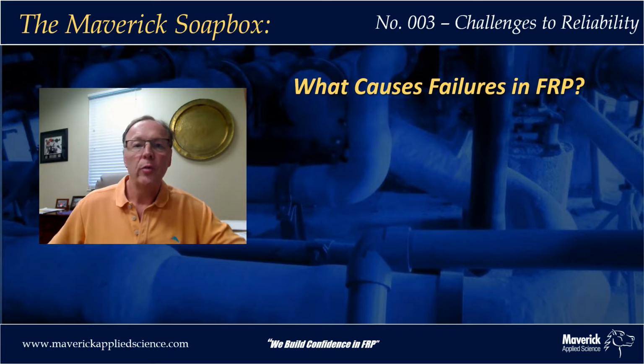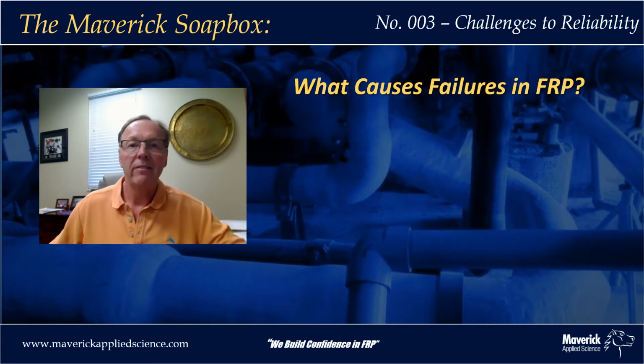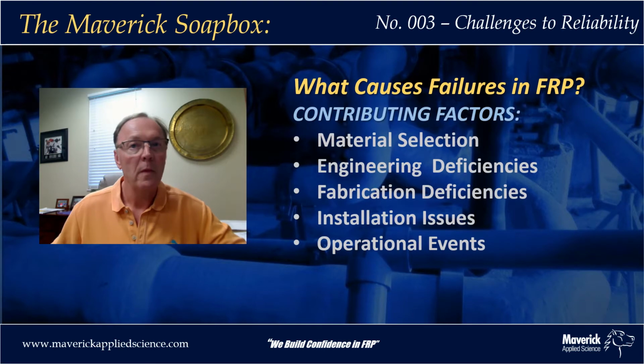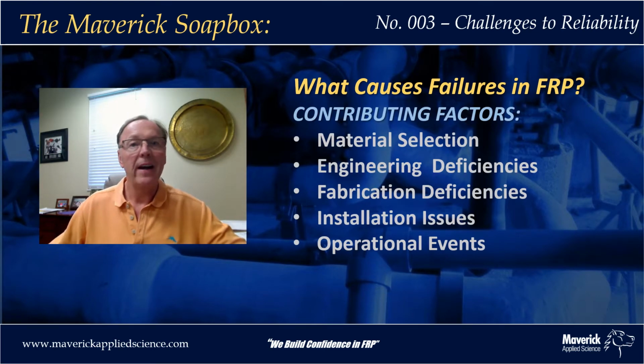In an internal research study, we examined 51 FRP failures to categorize contributing factors to those failures. Some of the failures go back as far as 1998, and the study is still ongoing today here at Maverick. So let's take a look at the results. We've identified 5 contributing factors that can lead to FRP failures: material selection, engineering deficiencies, fabrication deficiencies, installation issues, and operational events.